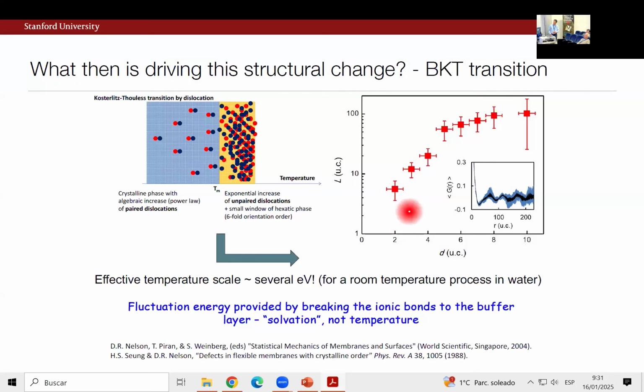As I'll explain, coming back to this in a moment, if we look at the crystalline coherence length of these sorts of membranes, you can see what your eyes told you: the coherence length was very long for greater than 5 unit cells of thickness, and then it exponentially collapses as we go down this road. And what's interesting is you can map this feature right onto these sorts of ideas.